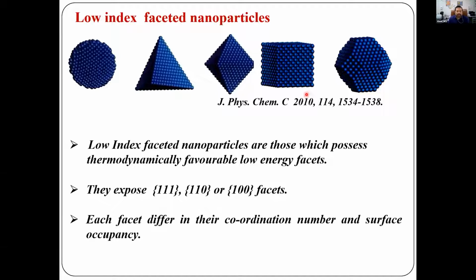Okay, so if you come back to nanoparticles, nanoparticles can be made in different forms. If you look at the nanoparticle that you generally make in the lab, these are in the form of an icosahedral particle, which looks spherical with a normal TEM. But you can also make particles which are triangular in shape, octahedral, cube shaped, and cuboctahedral particles. So these are basically low index faceted nanoparticles, which typically expose 111, 110, and 100 facets. And each facet has its typical coordination number associated with it.